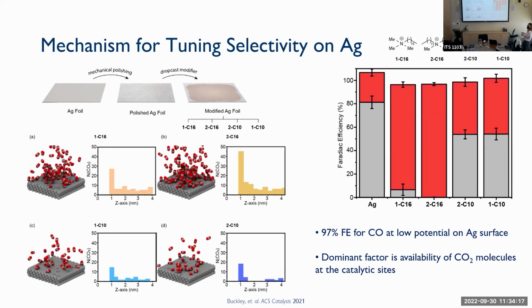Why? Because of the concentration of CO2 molecules at the surface. So all these different substituents are able to concentrate the CO2 locally in a different way. And the 2C16 derivative is able to actually give you many more CO2 molecules at the surface than, let's say, the 2C10 or the 1C10. And this tells you why you have more CO, because you actually have more availability of CO2 at the surface that can convert.